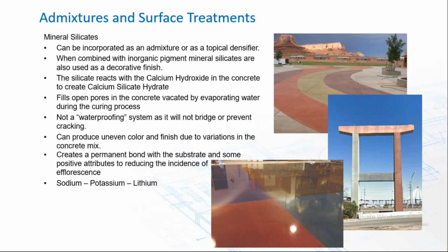When used as a coating, it can often produce an uneven color and finish due to the variations within the concrete mix. It does create a permanent bond with the substrate and has some positive attributes in reducing the incidence of efflorescence. And typically these densifiers incorporate sodium, potassium, or lithium silicate. And just a couple of examples of typical uses you might encounter there on the right.